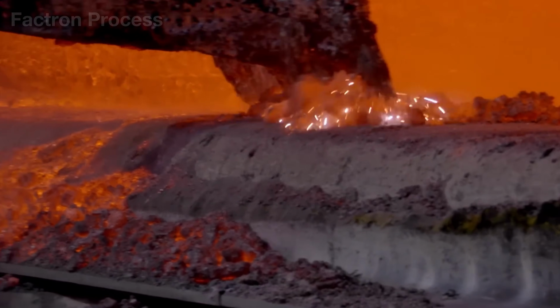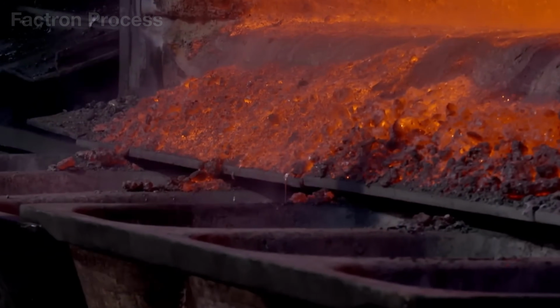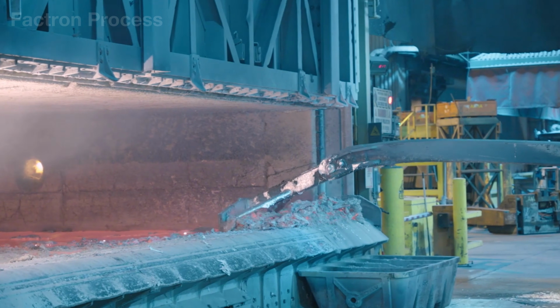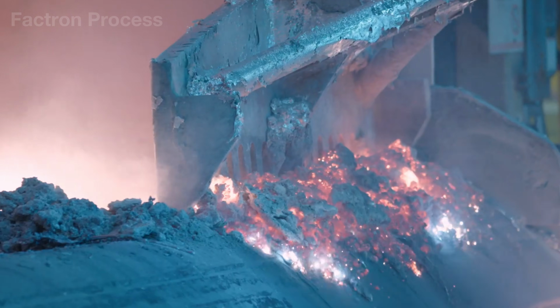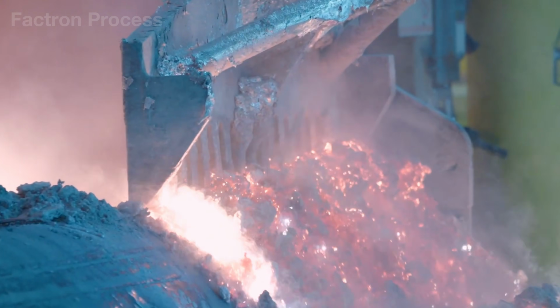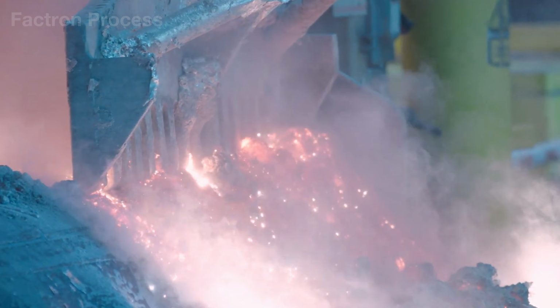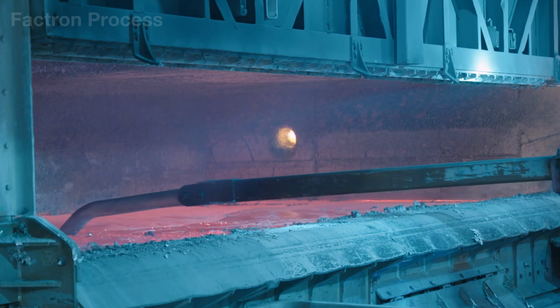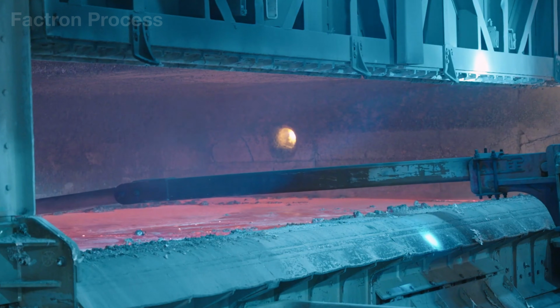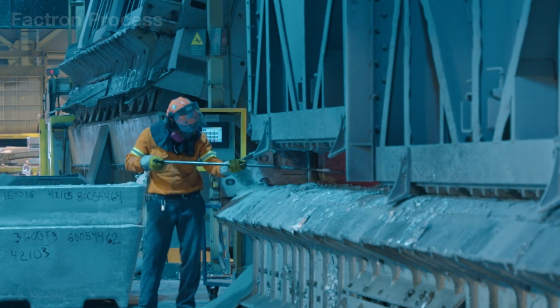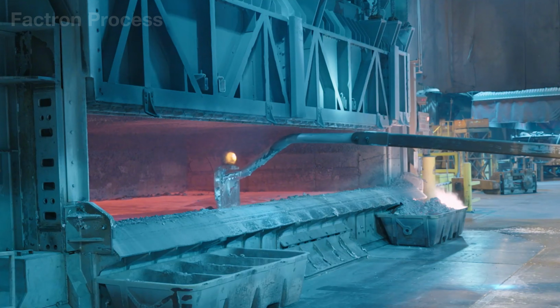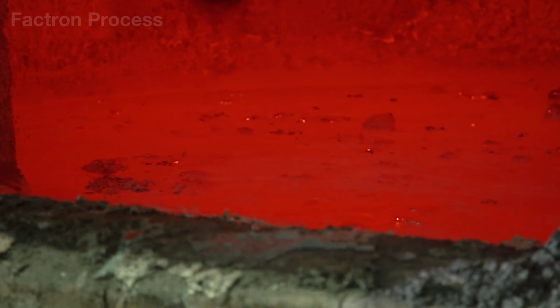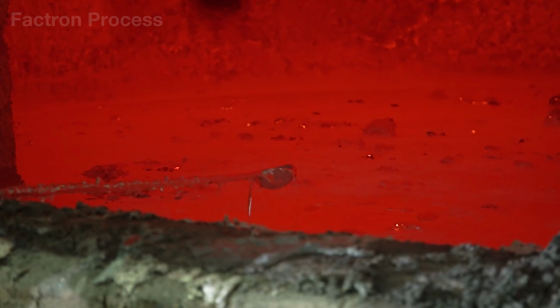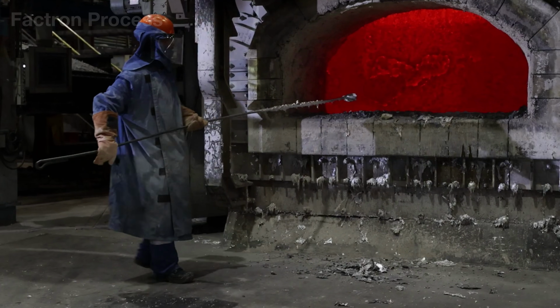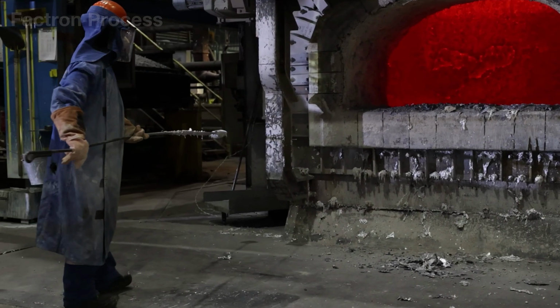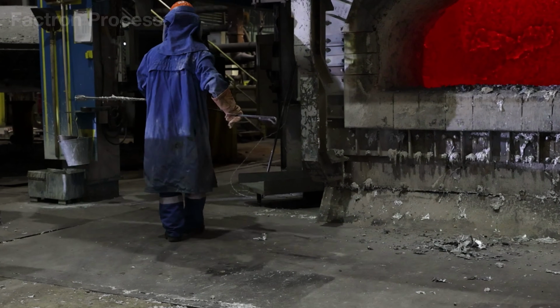Within just a few hours, thousands of individual can fragments have disappeared, replaced by a glowing pool of molten metal. But before casting can begin, its composition must first be carefully analyzed. In fact, recycling aluminum requires only about 5% of the energy needed to produce primary aluminum from ore. Even so, the furnace must be tightly controlled, because every kilogram of aluminum burned away into dross represents both lost material and wasted energy already spent melting it.